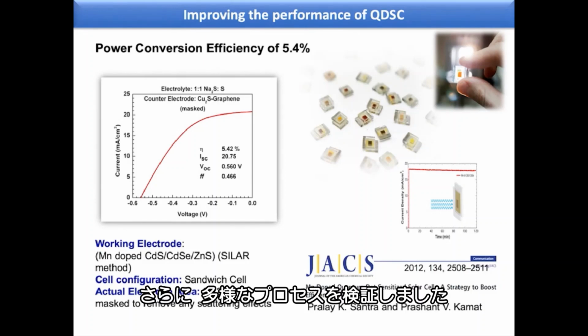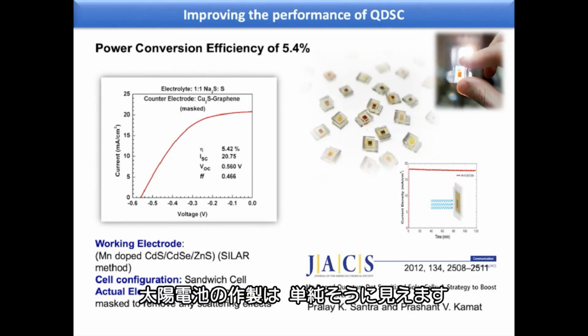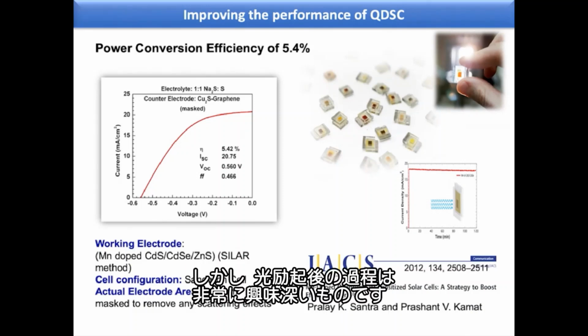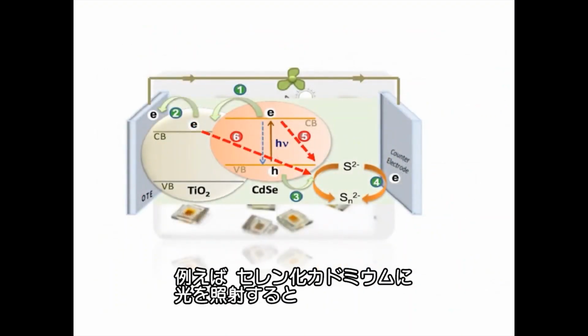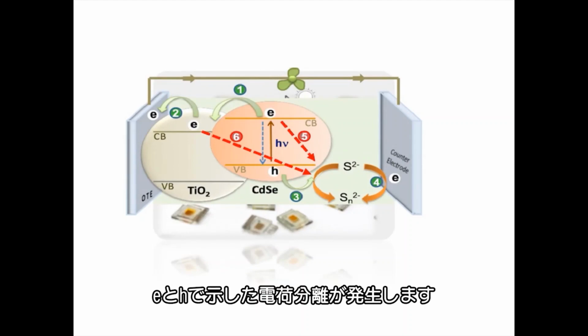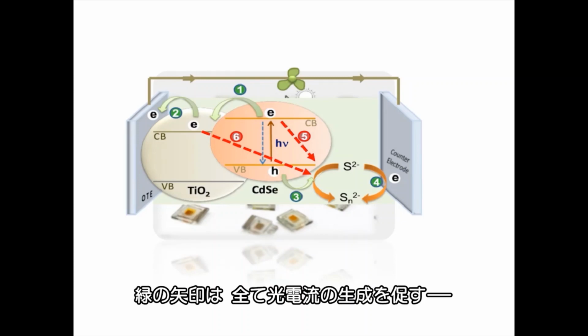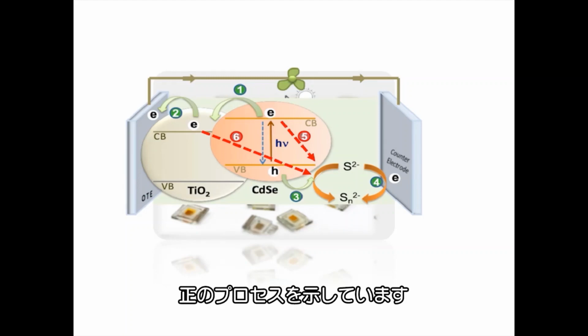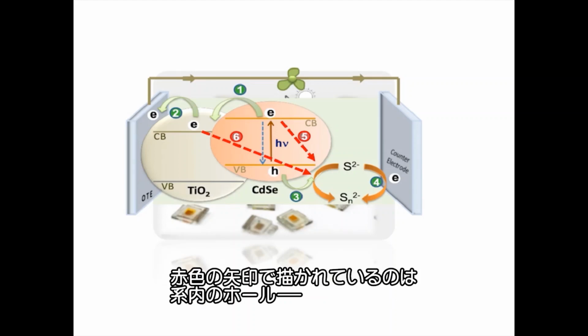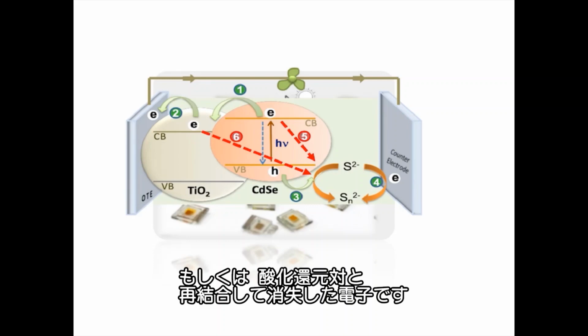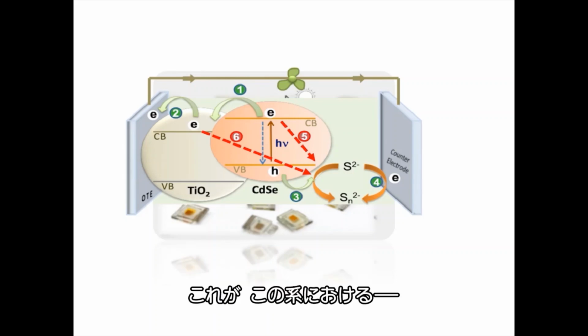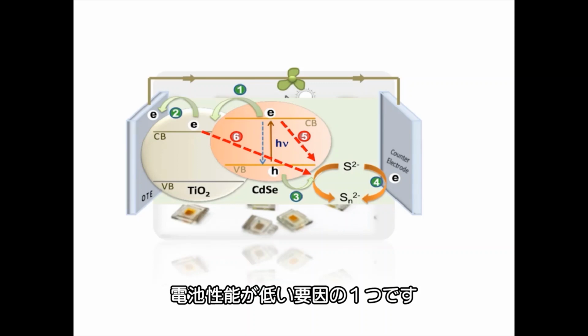And furthermore, we studied a variety of processes. Although it looks very simple to make a solar cell, the processes that follow the light excitation make this system very interesting. For example, once you shine the light on cadmium selenide, there is a charge separation represented by E and H, and the electron gets transferred to TiO2. Although all the green arrows show the positive processes that favor the photocurrent generation, the red arrows shown here show you the loss of electrons to recombination processes, either with the holes or with the redox couples in the system. So this is one of the reasons why these cells perform rather poorly in this system.